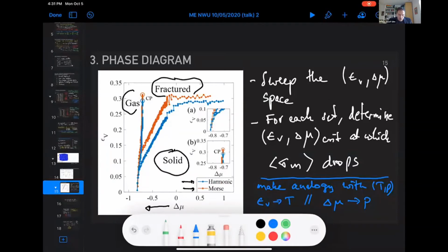Please note for engineers, typically when they do fracture mechanics, they are basically here at the zero chemical or radiation potential. And you see that there comes a critical value of the critical strain here, which is different for the Morse potential or the harmonic potential. They are quite different. So a really important point to be noted here is that epsilon V is basically an order parameter. So it becomes an order parameter in order to define the system.